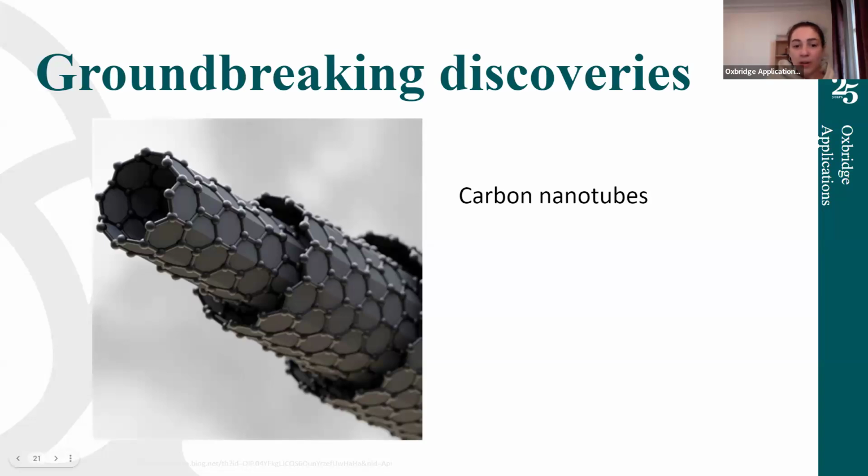Cylindrical carbon nanotubes have a very high aspect ratio. So that's the length to diameter value. So the diameters are from about 1 nanometer up to maybe tens of nanometers. And the lengths can even be in terms of millimeters. So it's a very, very high aspect ratio.